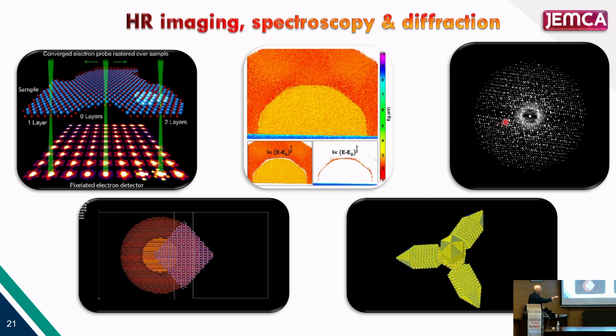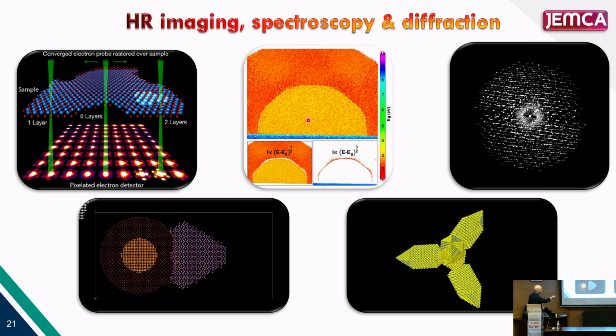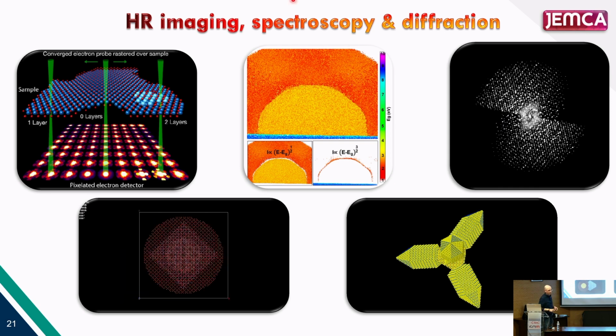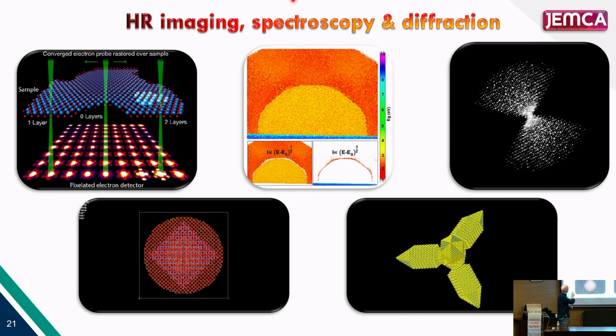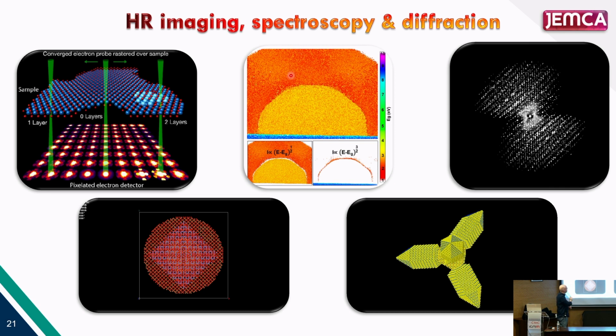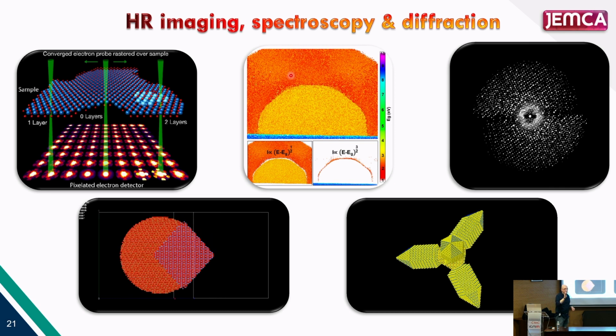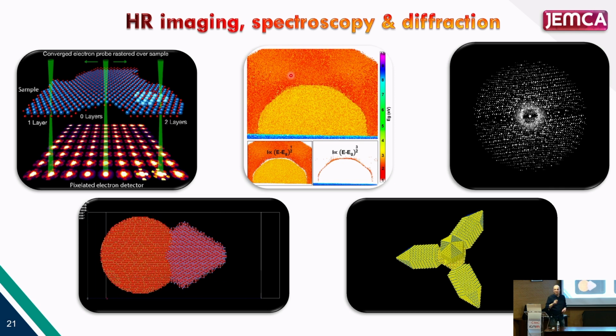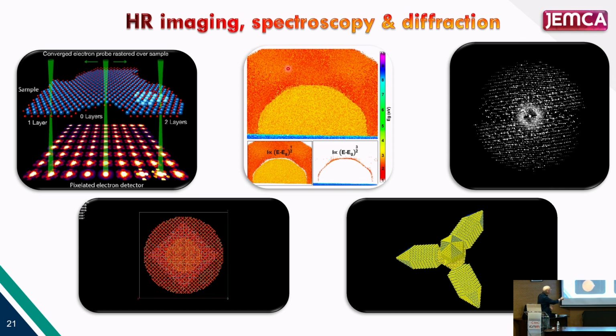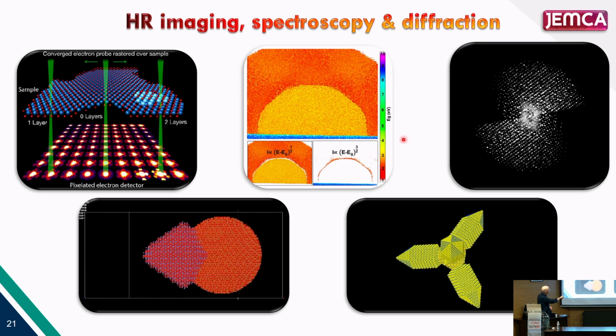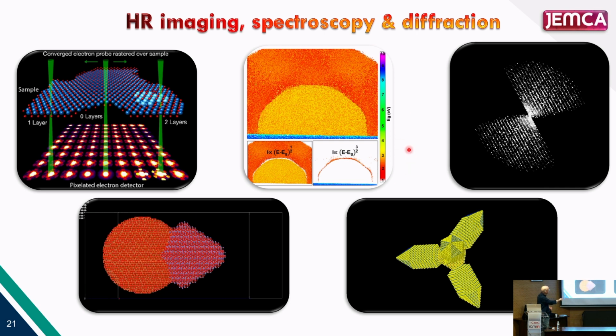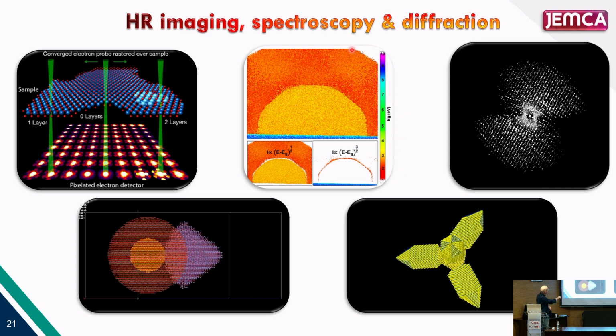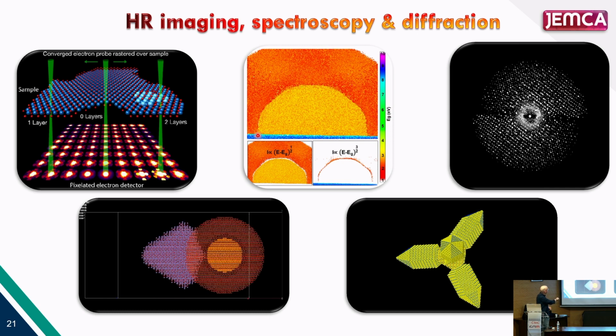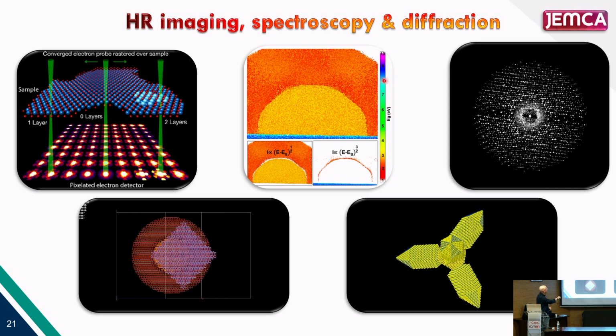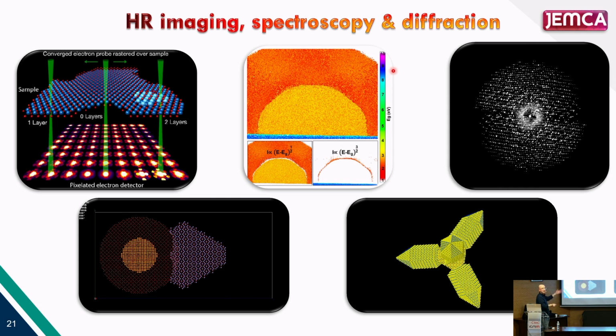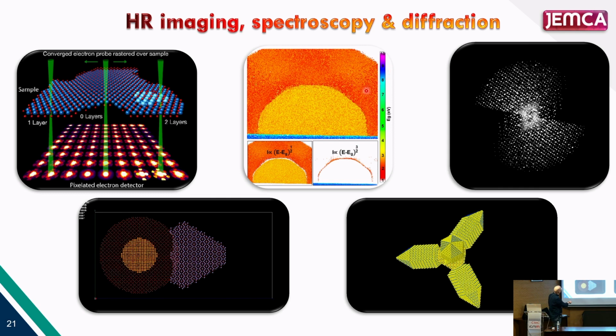Things that we have done recently, you can map the bandgap of your material, and you can go with resolutions. Every pixel here is below 1 nanometer, so it's around 0.9, 0.8 nanometer every pixel. So the resolution here is showing the energy of the bandgap. This is the scale here. This is zinc telluride and zinc selenide. This is alumina. You know, alumina is an insulator. You have a really high bandgap, but you can measure it.